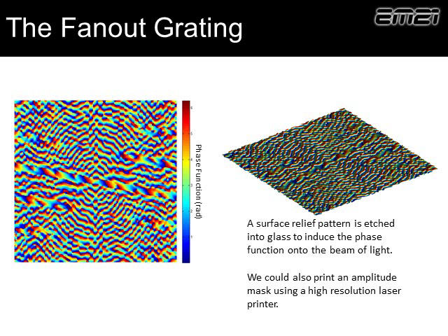Well, how do we do that? So we start with our phase, and we etch glass. So where we've etched, the light, when it propagates through that, won't see as much glass, and it actually comes out with advanced phase. Where we see mountains on here, the light will be traveling through more glass and traveling slower, and we're imparting phase. And we essentially etch this to the depth that we would get 90-degree phase out of that, and so we can convert our phase profile into an actual profile that we can etch into glass. Then if we pass a laser pointer through that, and this is just one little unit cell, we would actually repeat this over the diffractive optical element. We shine a laser pointer through that, and we get a pickaxe image. And that's how those pattern fan-outs work and how they're designed.